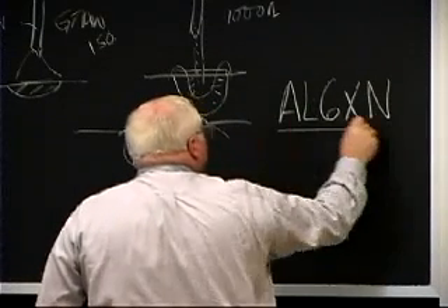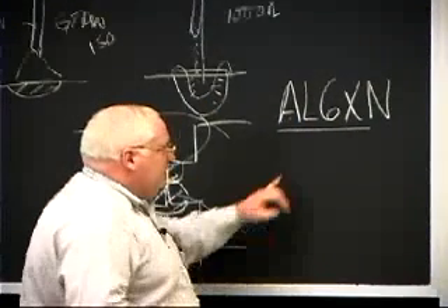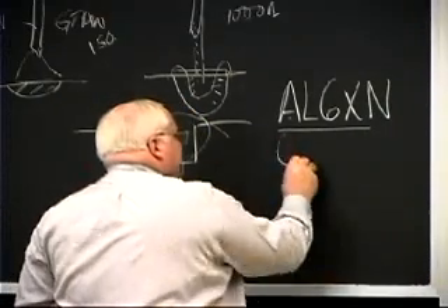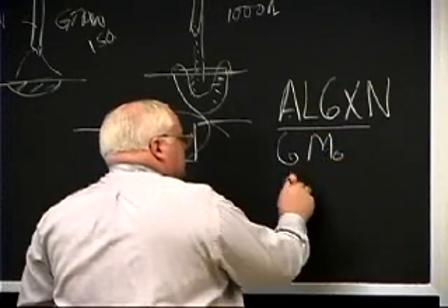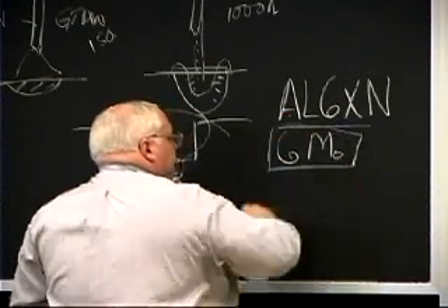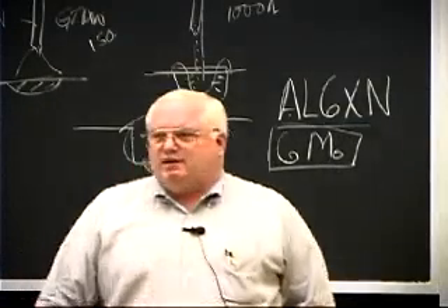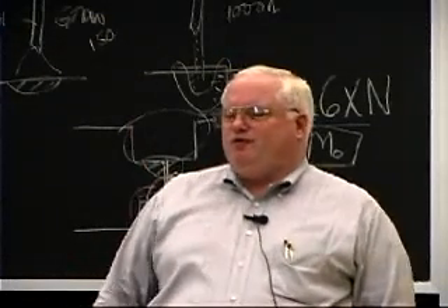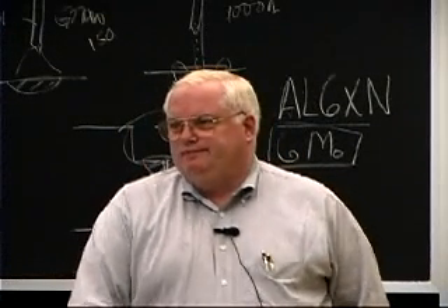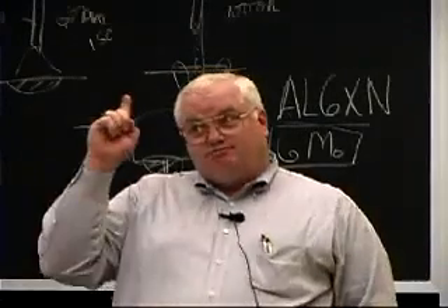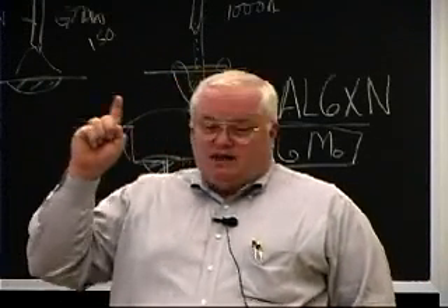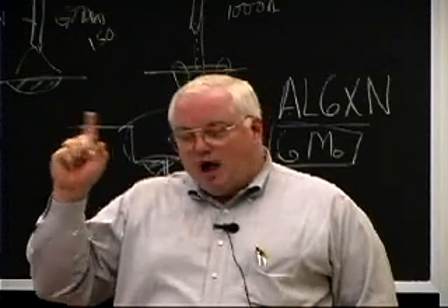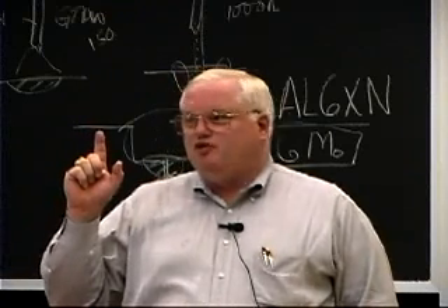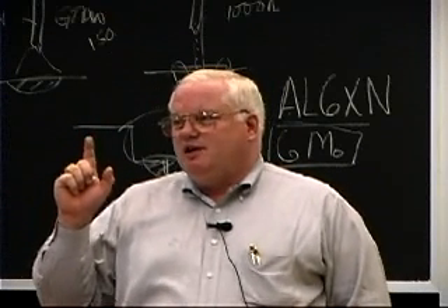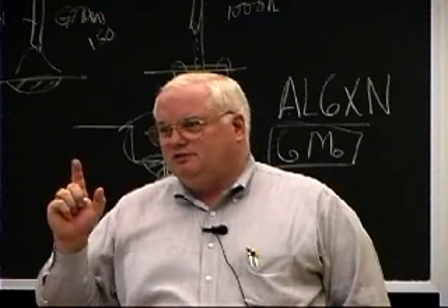This is an Allegheny Ludlum trademark, and in the 6XN, the 6 stands for the fact that it has 6% molybdenum in it. So it's a stainless steel, and that 6% molybdenum means this stainless steel is probably going to cost you about $3,000 to $4,000 a ton. Okay, but it's non-magnetic, and this stainless steel with that much molybdenum does not pit in seawater. Now, if you use 316 stainless steel, it would pit and stain in seawater, okay?